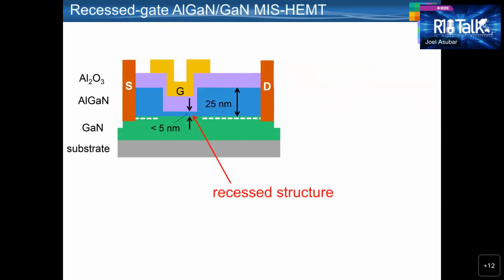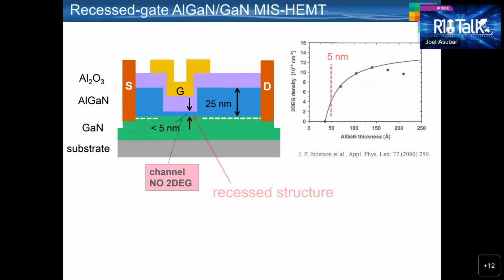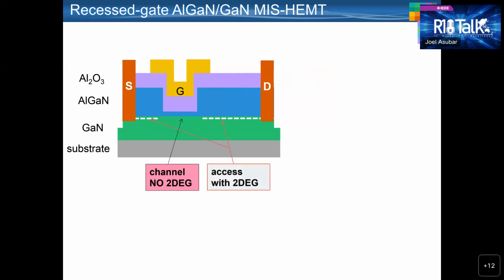One of the most studied device structures for obtaining normally off operation is this recess gate AlGaN MISHEMT. Here, the AlGaN layer under the gate is thinned down to deplete the 2DEG channel underneath the gate. The idea, as you can see here in this report, is that the thinner the AlGaN, the less is the density of the resulting 2DEG along the AlGaN-GaN interface. And thinning AlGaN to below 5 nanometers will eliminate the 2DEG along the AlGaN-GaN interface. Again, the AlGaN layer under the gate is thinned down to deplete the 2DEG in the channel region, while maintaining the existence of 2DEG in the access regions to maintain the low overall on resistance of the device.